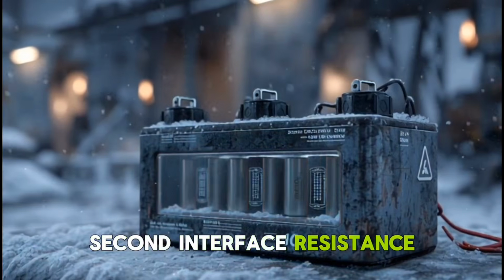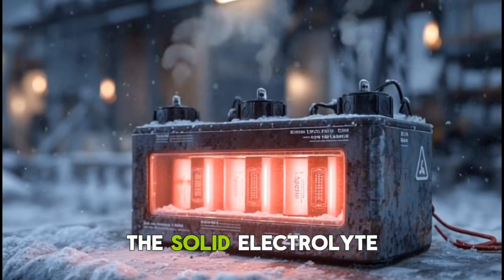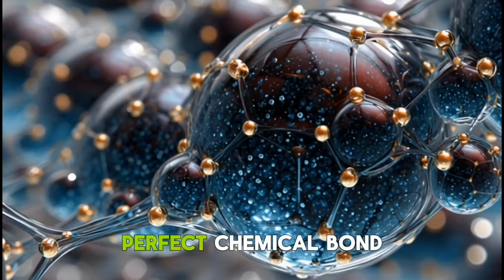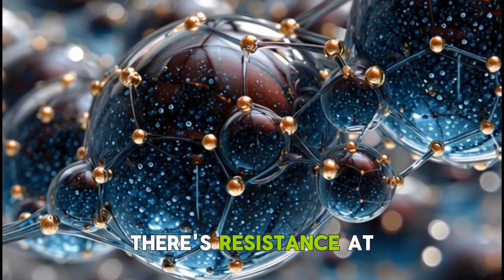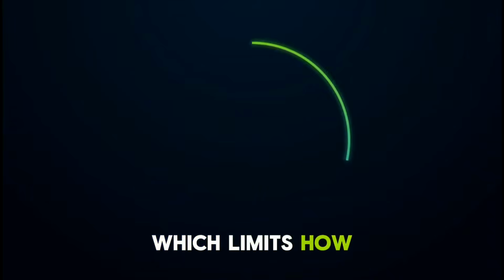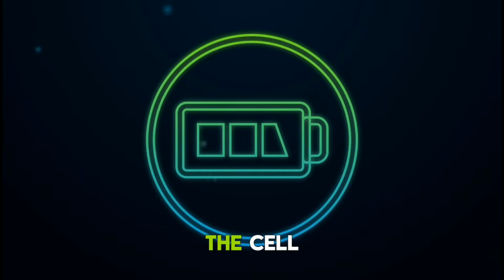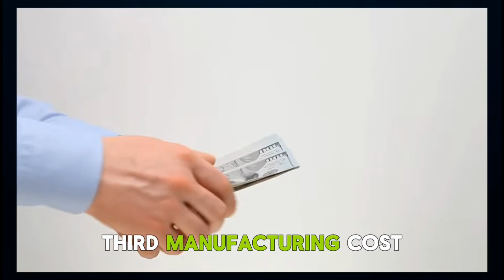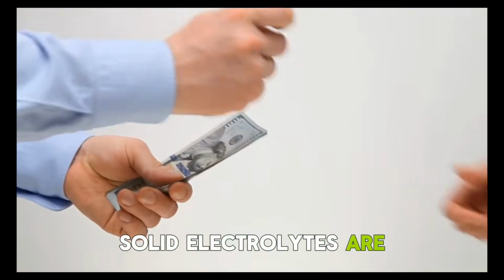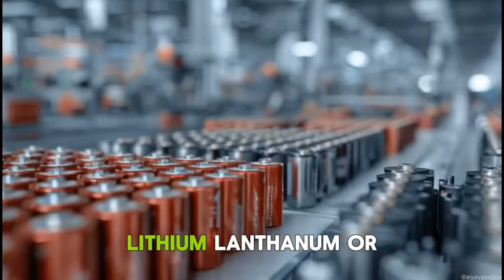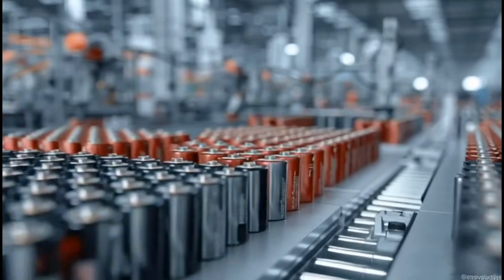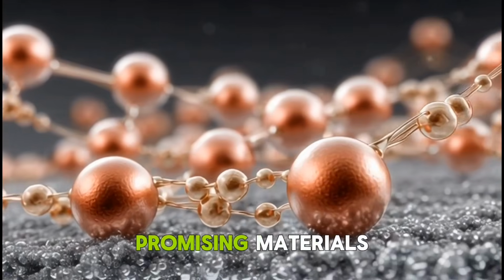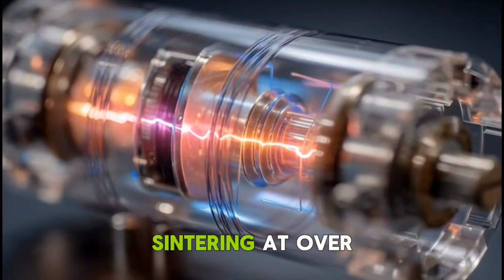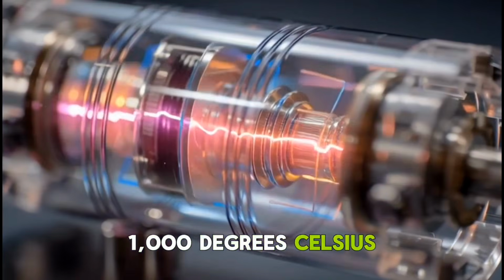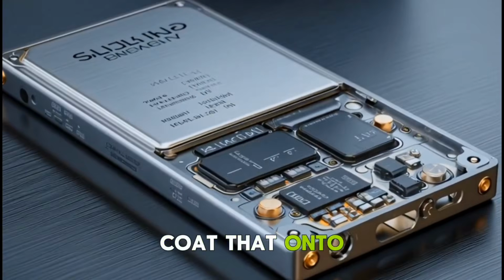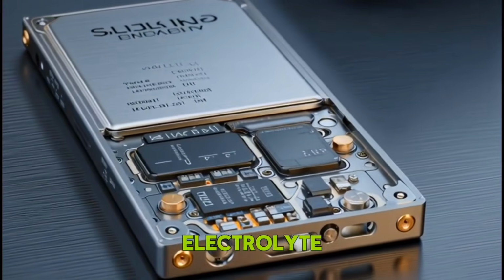Second, interface resistance. The boundary between the solid electrolyte and the electrode is not a perfect chemical bond. There's resistance at that interface, which limits how fast you can charge and discharge the cell. Third, manufacturing cost. Solid electrolytes are expensive to produce. Lithium lanthanum zirconium oxide, LLZO, is one of the most promising materials, but it requires sintering at over 1,000 degrees Celsius. You can't just coat that onto aluminum foil like you do with a liquid electrolyte.